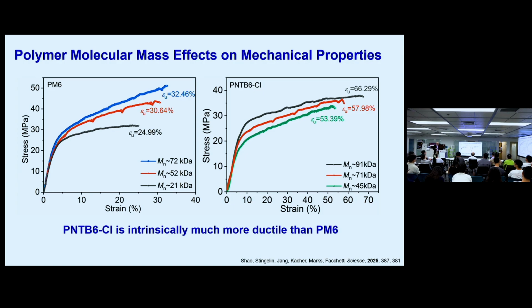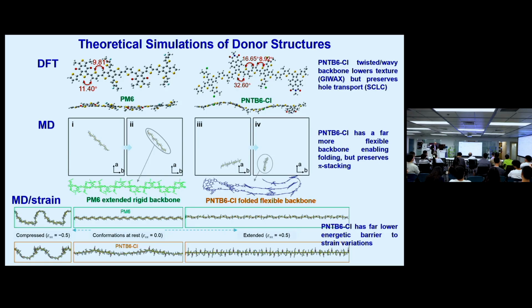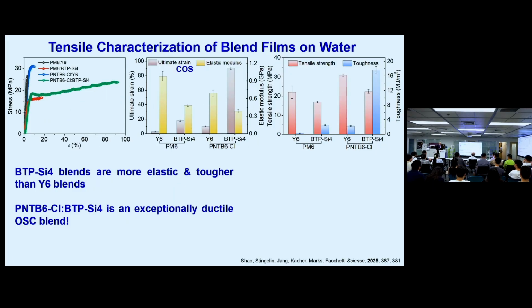But now let's go one step further. So the chlorinated one is intrinsically more ductile, but now let's make the blends, the photovoltaic blends. And this is some theoretical work, DFT and molecular dynamics. And one of the things you can look at just for the donors by themselves is, look at the one on the right, which has a more wavy conformation. That means it's more stretchable. And you can see that all the way in the molecular dynamics. So if a polymer has a very rigid backbone, it's going to be much harder to stretch. And you can actually, with molecular dynamics, begin to calculate as you begin to stretch it, what happens. And you can also define something called toughness, and this is sort of how much energy is needed to stretch it, and how much energy is spent doing that.